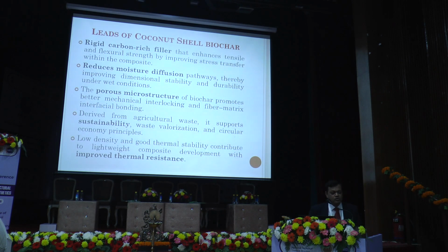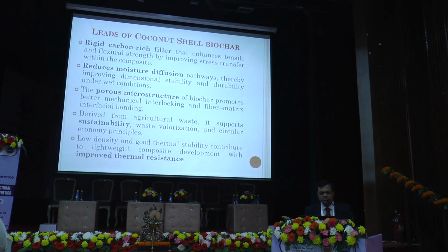So what are the merits of coconut shell biochar? Coconut shell biochar is a rigid, carbon-rich filler that enhances the tensile and flexural strength by improving stress transfer within the composite. It reduces the moisture diffusion pathways, thereby improving the dimensional stability. The porous microstructure of biochar promotes better mechanical interlocking and fiber-matrix interfacial bonding.